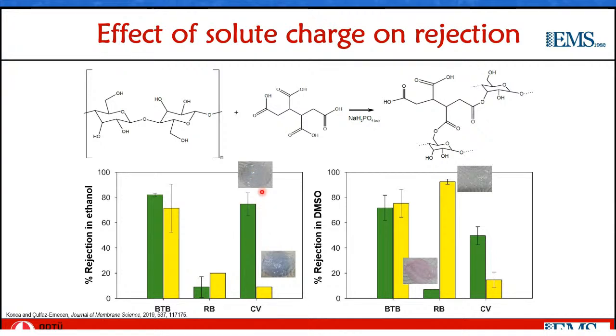a significant difference between the sorption of the probe on the membrane, where small rejection was correlated with high sorption here and here, as you see. Here, I should note that these rejections were measured after any sorption on the membrane was equilibrated and a stable rejection was observed. So the number that I report for rejection is actually the true membrane rejection and not affected by the sorption of the solute on the membrane. And this actually implies that a solution diffusion mechanism is governing the transport of the solutes, in that the solute that is sorbed more is more permeable. You can think of this as a solubility of the probe in the membrane, and hence a more permeable dye means a lower rejection for this dye.